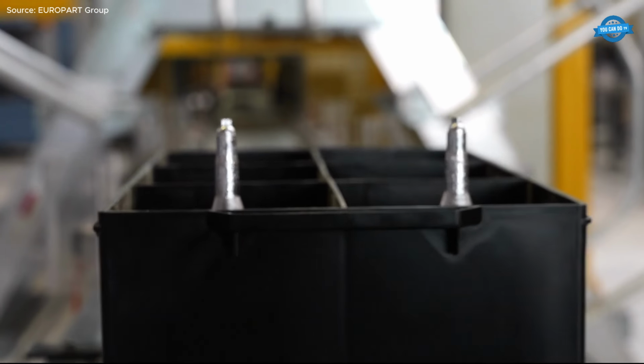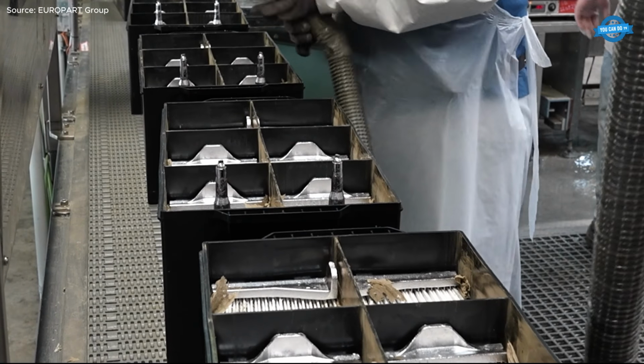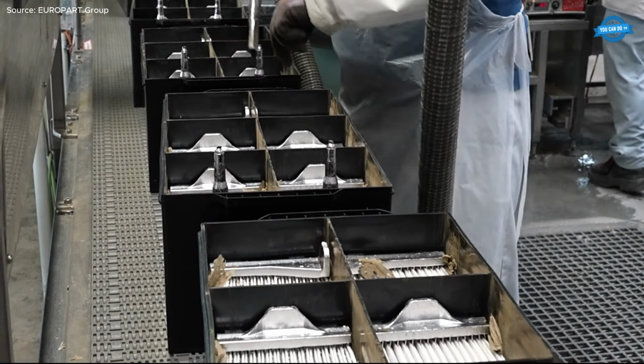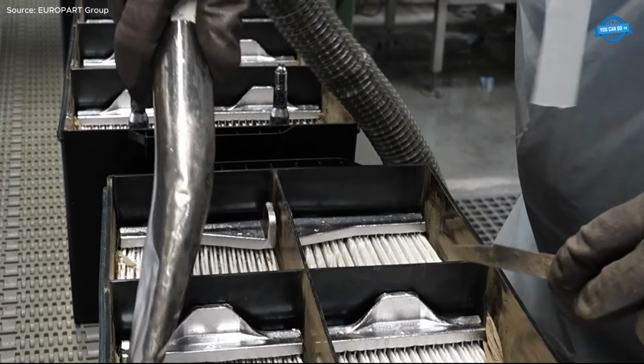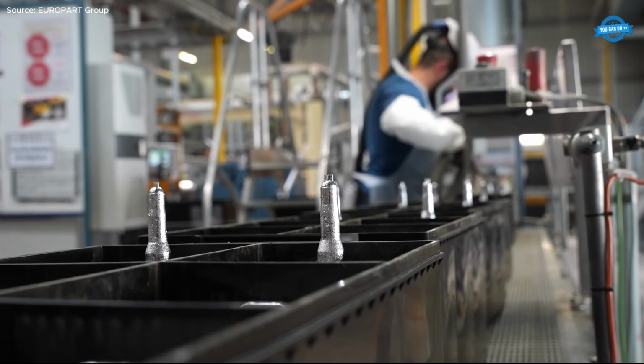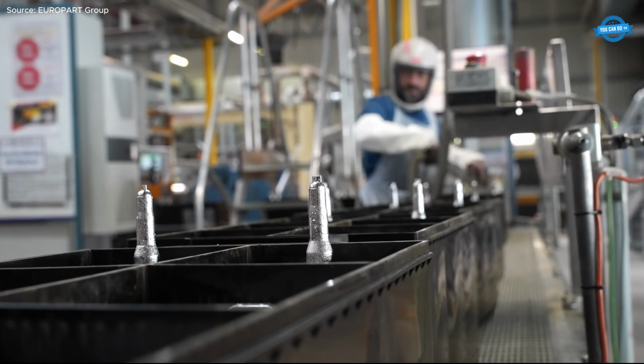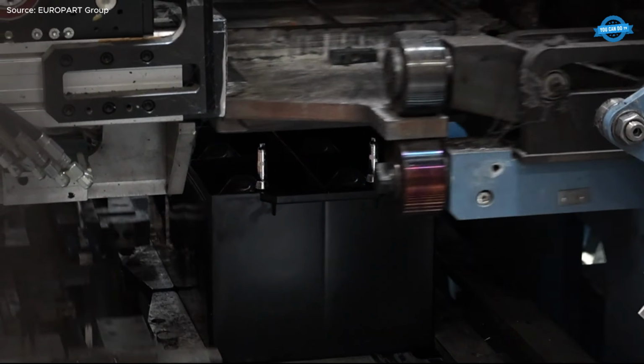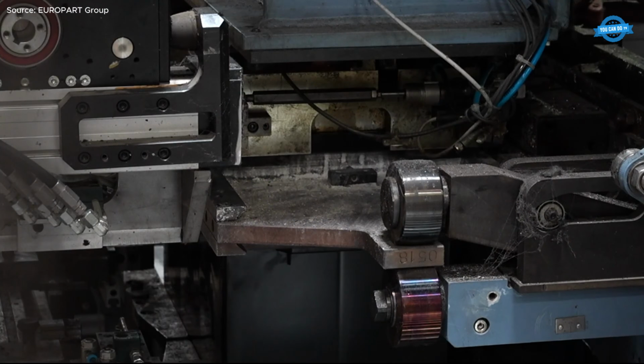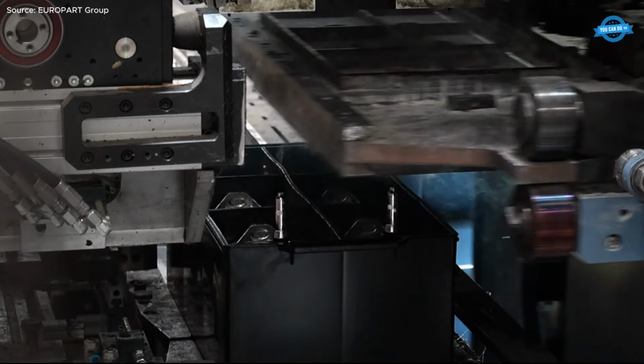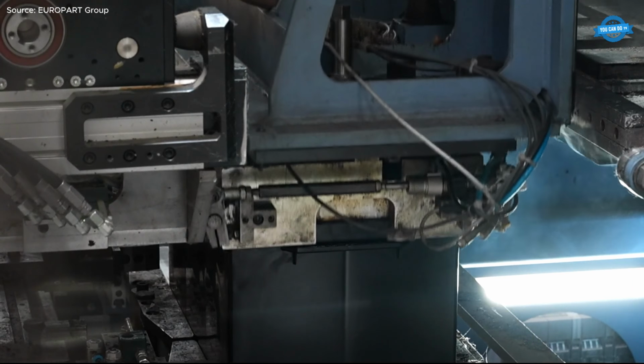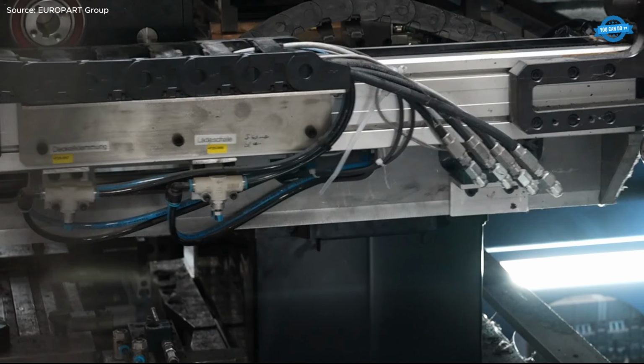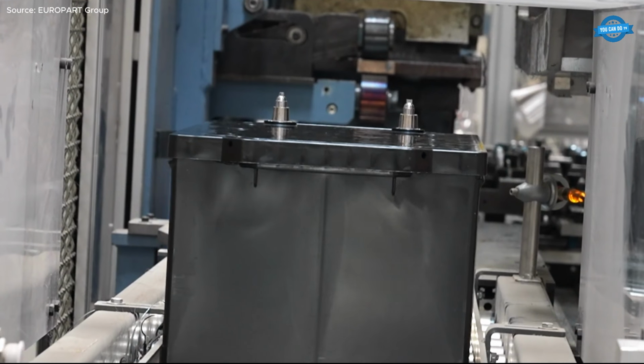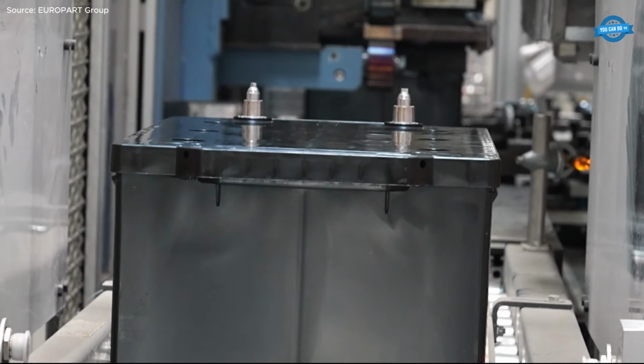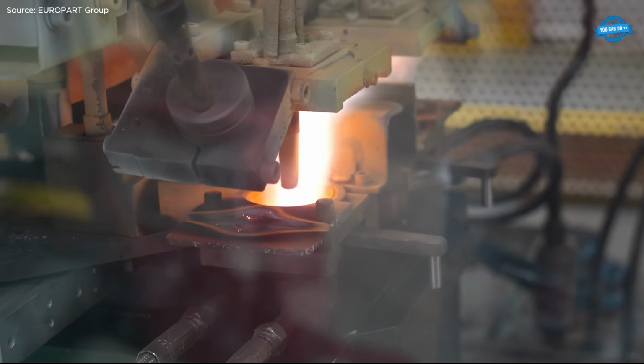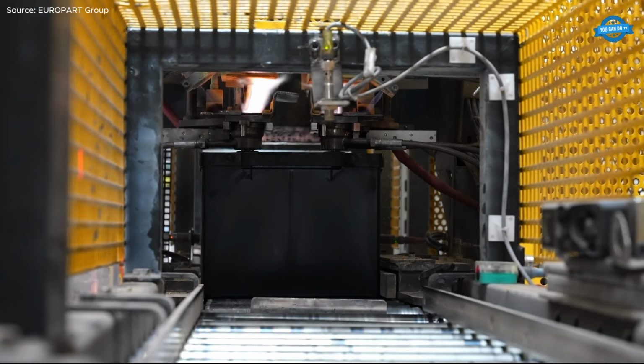Assembly integrates separators, cases, lids, and plate groups. Positive plates wrapped in glass fleece are paired with negatives and joined using molten lead strap casting. 6 plate groups are inserted into the 6 cells of each housing, followed by short-circuit testing, cell welding, and lid sealing. After terminal soldering, each unit receives sulfuric acid, initiating the chemical system. Batteries then enter water-cooled formation charging, which may take hours or days depending on the model.